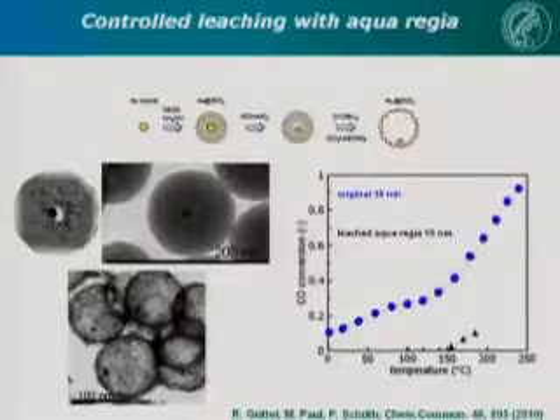You can actually take all the gold out, then you have silica particles with a tiny little 15 nanometer hole in the center, which you can then refill with something else. I don't want to discuss that today. So you can, by controlled leaching, actually reduce the size. But if you do that, well, this is the conversion curve for the native material. But if you leach, you lose all the activity.